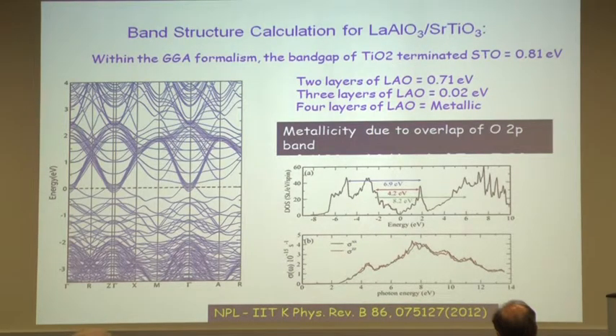And the question is, why is this sensitive only to UV light? So we did some band structure calculations for the interface, and it turns out that when I take the TiO2 terminated strontium titanate surface, my band gap is only 0.81 electron volt at the surface. And once I put 2 unit cells of LaO, this reduces to 0.7. If I put 3, it reduces to 0.02. And finally, at 4 unit cells of LaO, it actually becomes a metal. And that's what the experimental observation is.